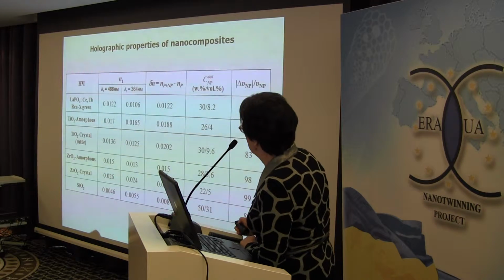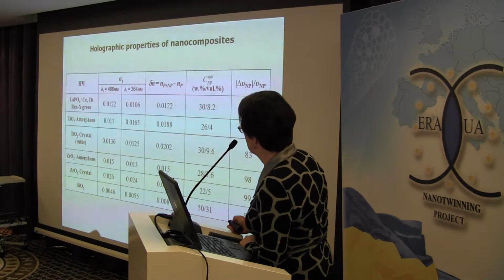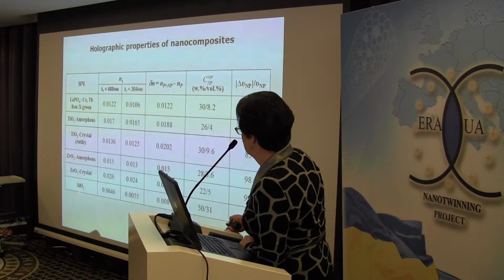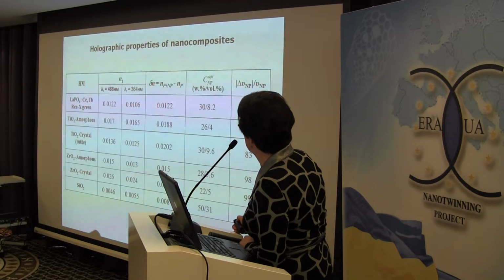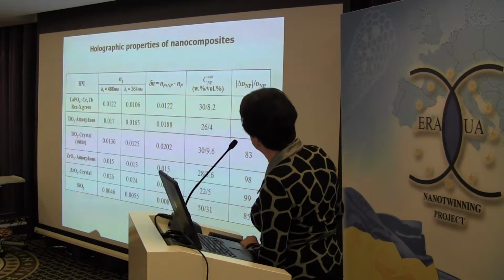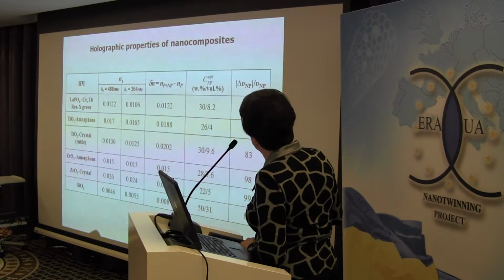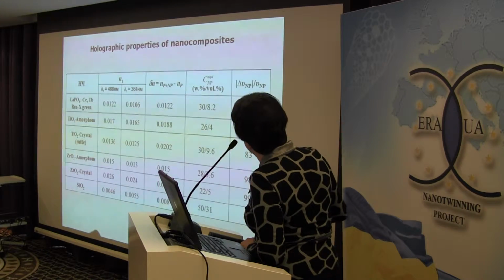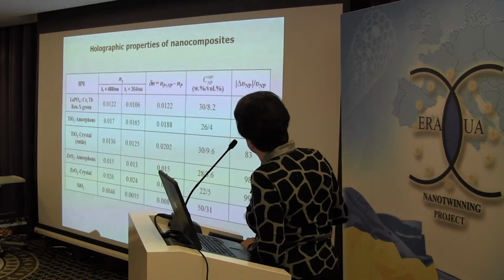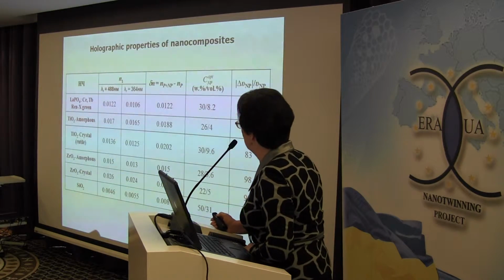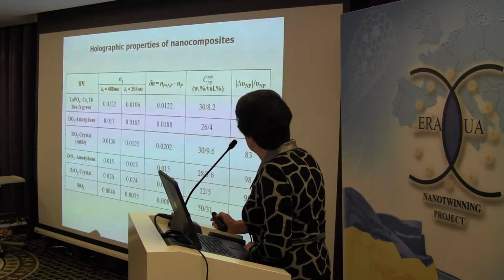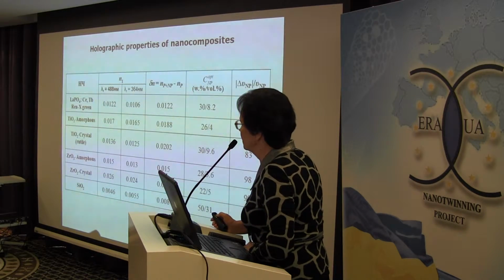As you can see, for all cases except silicon oxide nanoparticles, the obtained value of n1 approached the theoretical limit. And relative modulation of concentration is close to 90%. That means that all particles are located in the one planes of the holographic gratings.